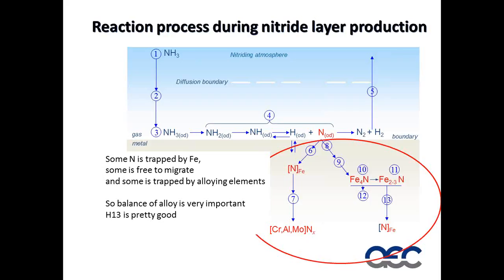However, as with the white layer, it was too hard, and it gave us a lot of problems with cracking and flaking. Now I understand there are better steels around now with a little aluminium in them that can get over this problem. But generally, H13 is pretty good at this. It has a little bit of all the good stuff in it, and the nitrogen reacts with this and is trapped in the surface. So that's the three places our nitrogen goes.